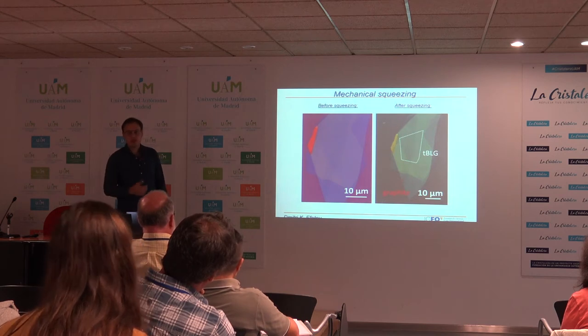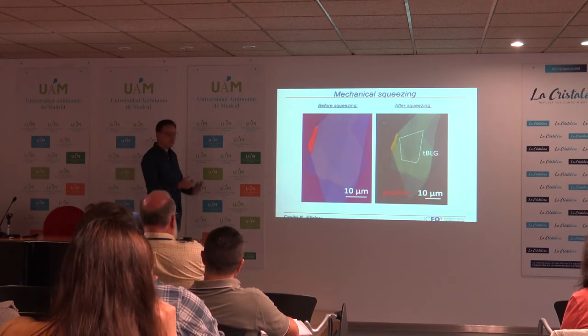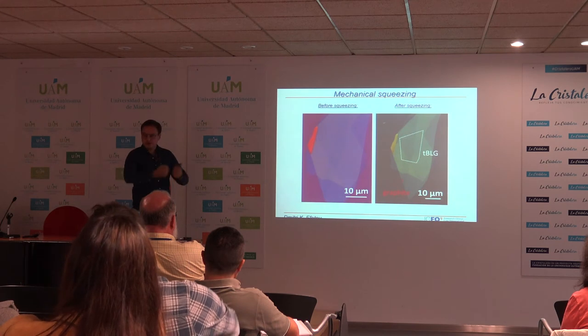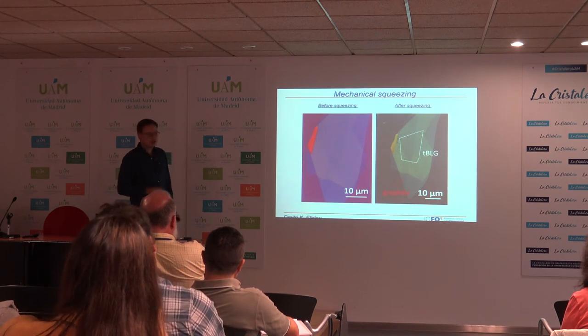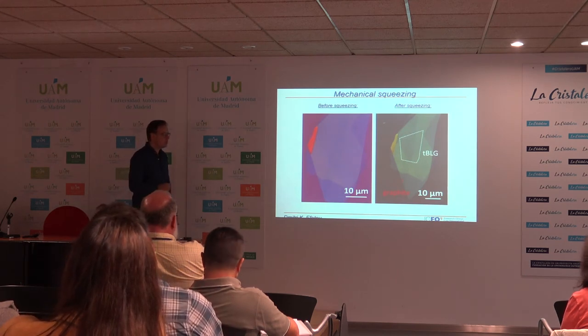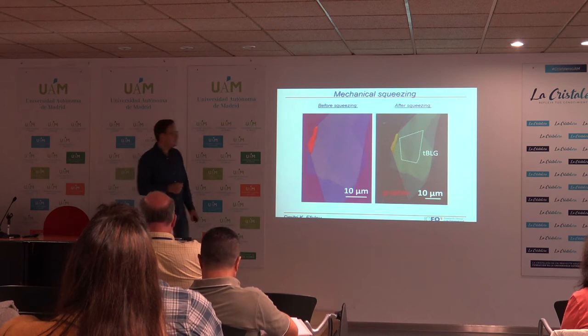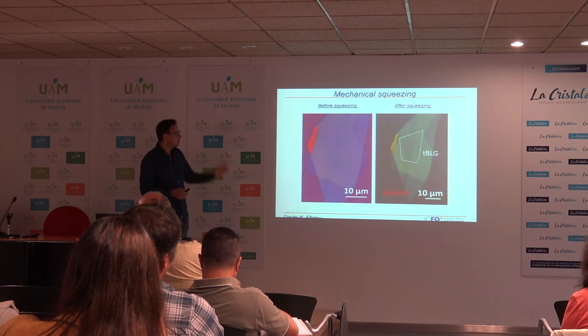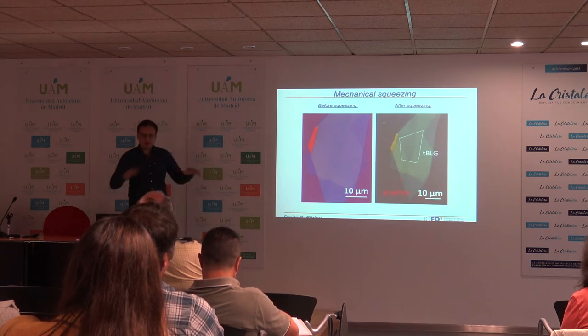And this happens here. But of course, in terms of twist angle, these air bubbles are strain centers. So they're really changing the surroundings, they're changing the twist angle of the device. So what we have succeeded in doing, we have succeeded in really squeezing these bubbles out, releasing all the strain in the system.